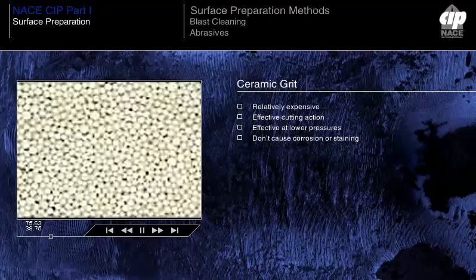These ceramic grits are particularly well suited to blast preparation of thin metal surfaces, which show buckling or distortion if blasted with chilled iron grit at conventional blast pressures. Finally, as these ceramic grits are essentially inert to normal corrosive influences, they can be safely used to grit blast stainless steel or non-ferrous material surfaces without causing rust staining, discoloration, or bimetallic corrosion.